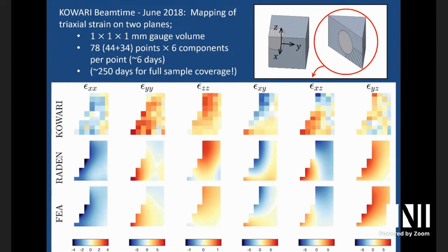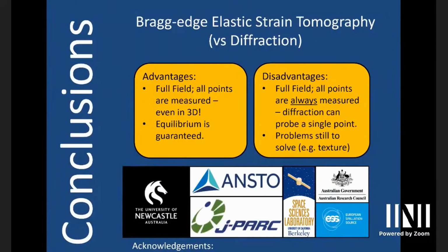So in 2D, it's about the same, right? We can probe every point, or we can do tomography, and it'll work out to similar orders of magnitude of time. But in 3D, there's just no comparison. Tomography will give you results way quicker, and much more information than you would get through diffraction. All right, so I think I might pull up there because I'm running out of time.